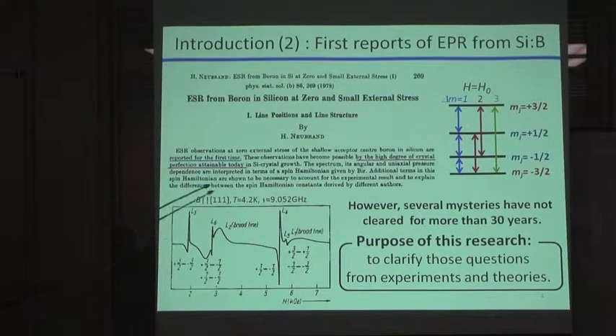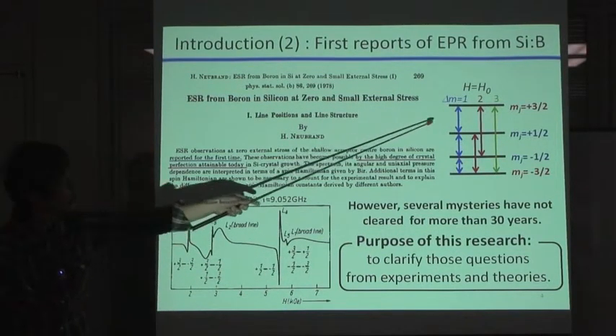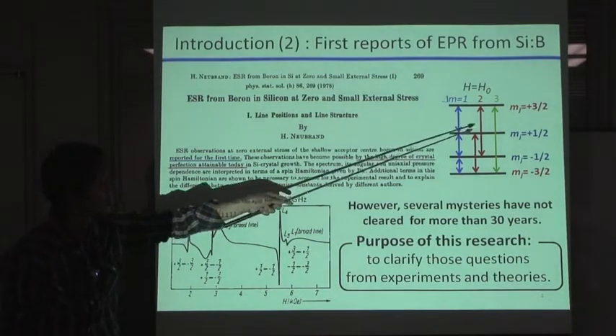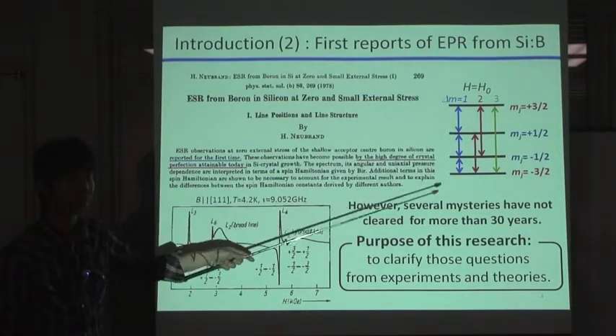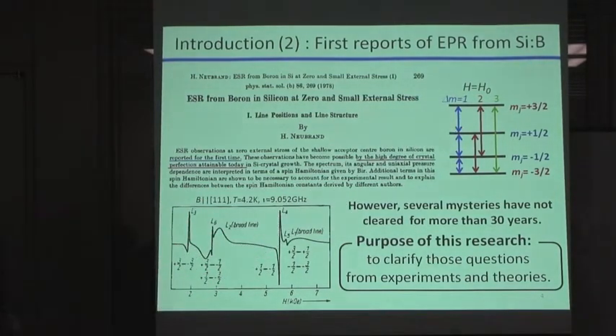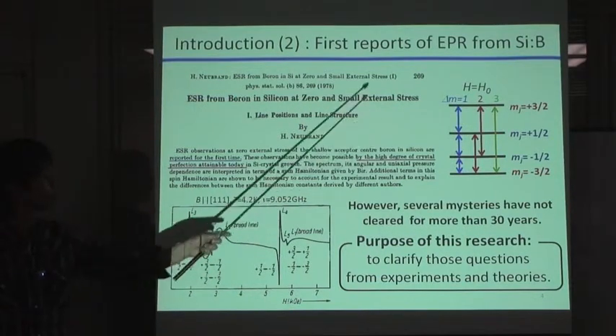when the crystal-growing technique was improved enough to make a single crystal with very high crystal perfection. Here, you can see the overview of EPR spectrum measured by Neubrand with natural silicon sample. So, you can see totally six transition lines corresponding to each splitting in the boron's four-level system. So, he has successfully observed all of the resonance signals from this sample.